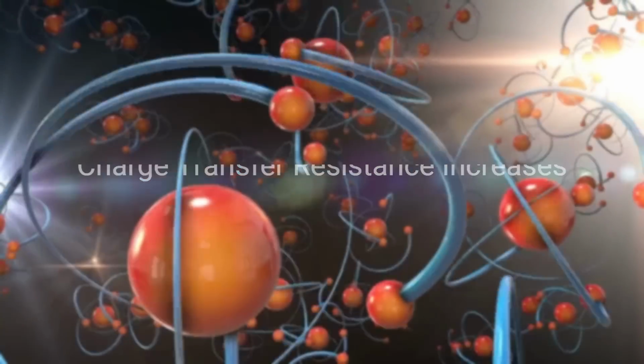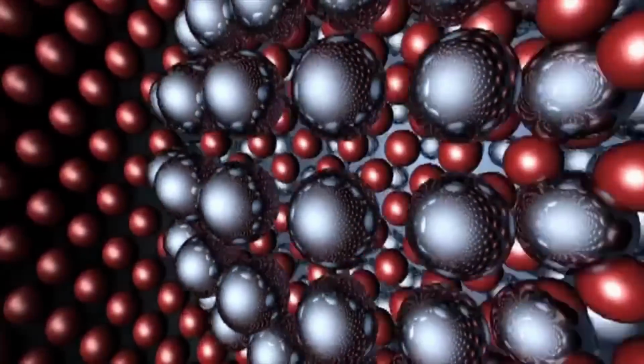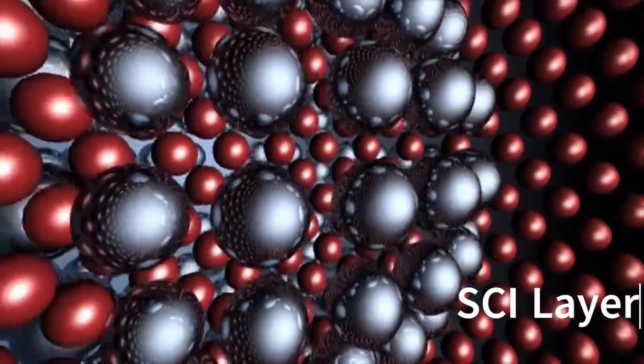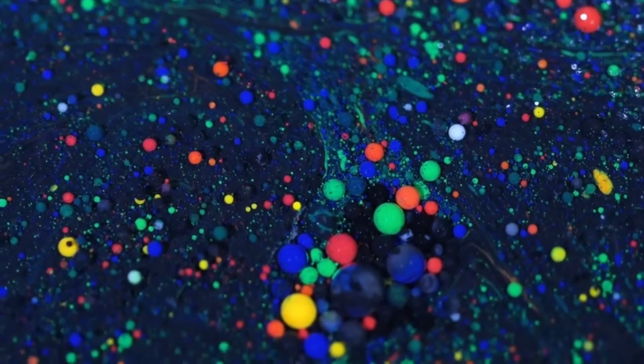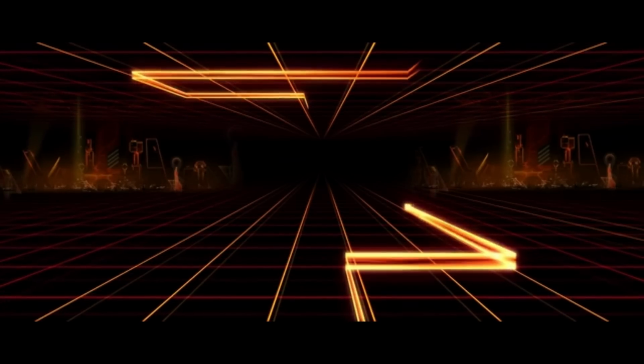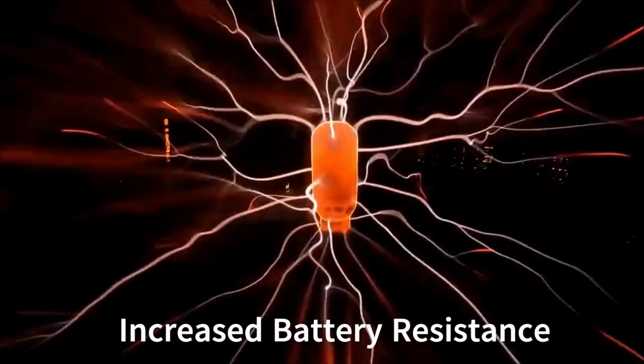As the temperature rises, the charge transfer resistance at the electrode-electrolyte interface and solid-electrolyte interface increases in lithium-ion batteries. It occurs because the solid-electrolyte interface, the SEI layer, starts getting thicker with higher temperature, which leads to reduced ionic diffusion. Hence, more heat is generated due to the movement of lithium ions and power loss increases further. Unfortunately, excessive heat can damage battery components, especially the cathode, where the oxidation of the electrolyte takes place, and it increases the battery resistance, which further reduces the battery efficiency. Additionally, certain electrolytes like lithium hexafluorophosphate decompose at elevated temperatures.